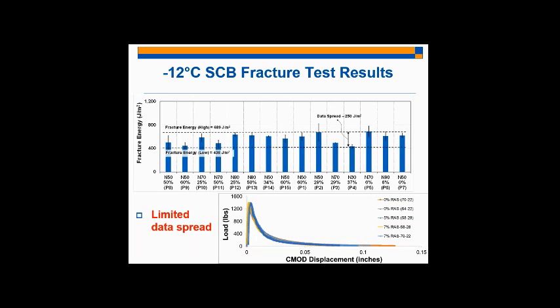Some of them were replacing 60% of the binder with recycled content. And the spread in our data is not too significant. You can see here that it's very limited. It's a value of 250 joules per meter squared, which is not too different from the experimental error that we experience.